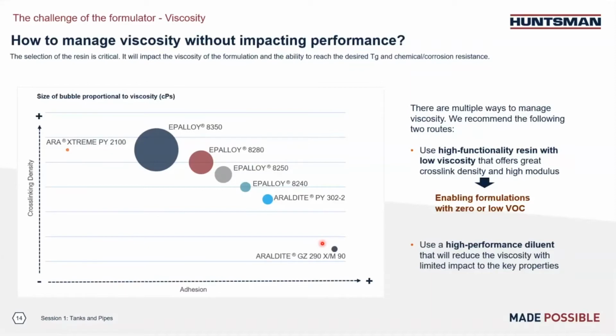If we're looking for good chemical resistance systems, we want to consider Novolac. And we have several great Novolac epoxy resins you can choose. For example, we have EPALLOY 8350, which has high functionality, about 3.6. But if we look at the bubble size, this one also has a very high viscosity. We also have EPALLOY 8240, for example. So this one has a lower viscosity, and the functionality is still about 2.4. So we can have a good crosslinking density, but without a very high viscosity to manage.